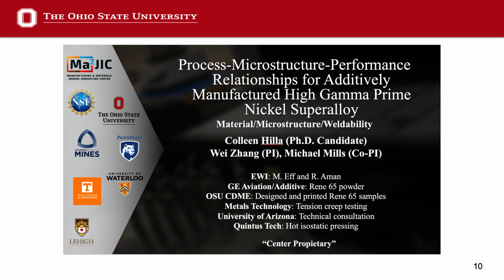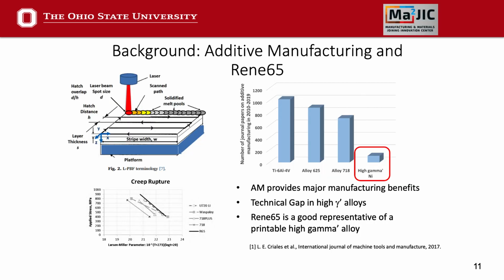Yeah, so there's a lot of interesting benefits that you can get through additive manufacturing, but we found that there's a large technical gap in terms of looking at these higher gamma prime alloys, which are really useful for a lot of aerospace applications. One of the main issues with these alloys, though, is that they're not very printable. You experience a lot of solidification cracking and issues with printability. So what we found is that Rene 65 does a good job filling that gap. It's pretty printable, so we don't experience a lot of these cracking issues, and we can study these higher gamma prime alloy systems using Rene 65.